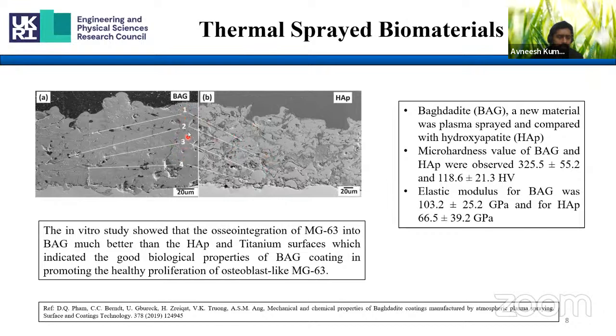So these numbers are nothing but some general features of plasma sprayed coatings. Number one shows the micro cracks developed in the coatings because after remelting, they cooled down, and because of that, some stress is generated in the coating, and then these cracks develop. Then number two shows that there are some micropores also. Then some unmelted particles are also there.